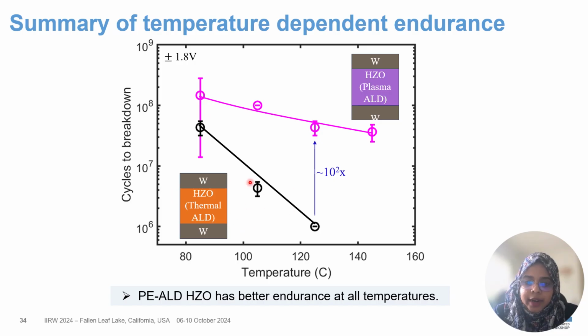What we're seeing is that as soon as we're entering higher temperature, the thermal ALD device is showing worse endurance. However, we are getting enhanced endurance in our plasma ALD device at a wide range of temperature, and we are getting an enhancement of endurance of up to 2 orders of magnitude at 125 degrees Celsius. Now, why did I mention 125 degrees Celsius? Because according to the JEDEC standard, for 3D IC integration, memories have to be reliable at 125 degrees Celsius.